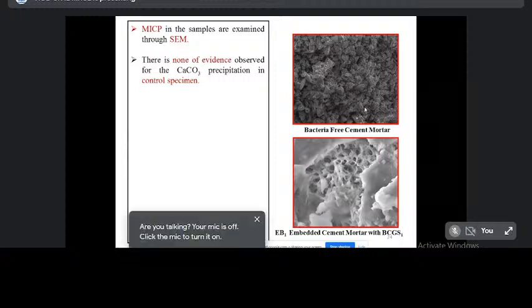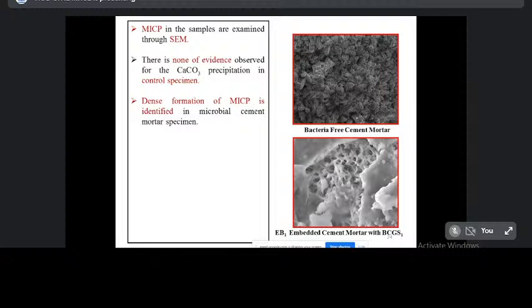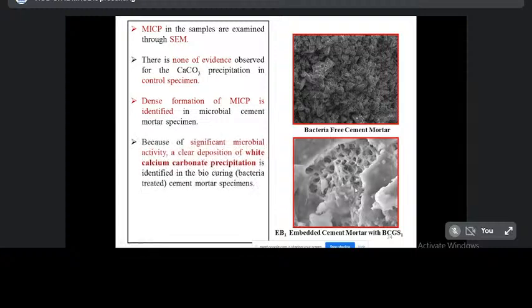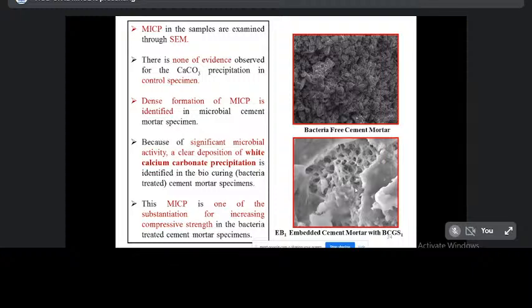Here, no white deposit is observed, but dense formation of MICP is identified in the microbial cement mortar specimen. The second photo shows the dense formation of white deposit. It is called calcium carbonate. Because of the significant bacterial activity, a clear deposition of white calcium carbonate precipitation is identified in the biocuring cement mortar specimen. This MICP is one of the substantial contributors to increasing compressive strength in the bacteria-treated cement mortar specimen.